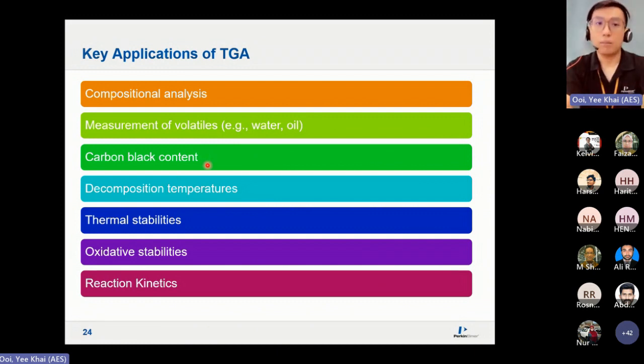Then carbon black, this is usually for polymer people who use carbon black as a strengthener or additive, okay, in their polymers. Or for those running, for example, graphene, graphite, elastomers, then you do see these as well. But in order to do this, oxygen is required. Then you have your decomposition temperature coming from the weight loss or your thermogram. Then thermal stability means how well your material holds up: the higher the temperature at which your material starts to decompose, the higher the thermal stability. Oxidative stability requires oxygen as well, meaning how long the material can sustain oxidation, okay?